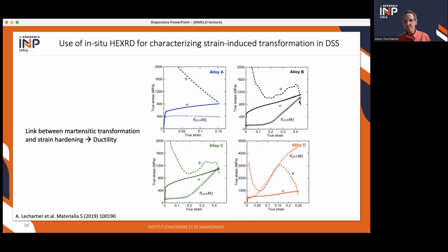So really, the kinetics of the phase transformation helps you to design the strain hardening rate so that it keeps just above sigma, but not too high, because then it's useless to have such a high hardening rate at a point where you're still far from ductile failure.